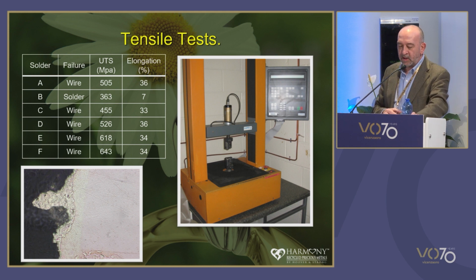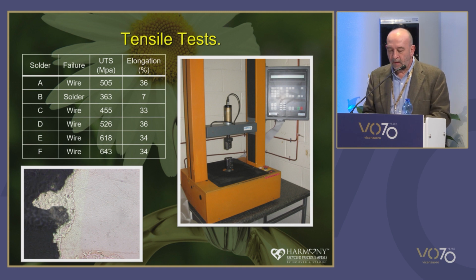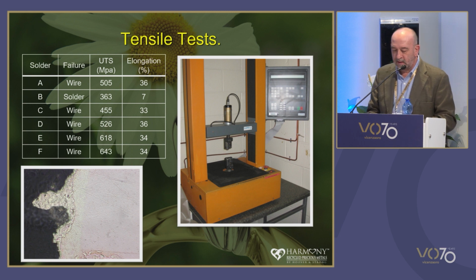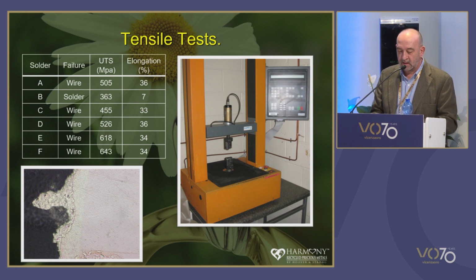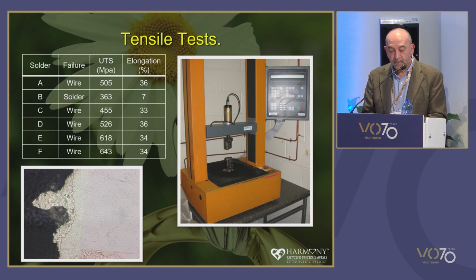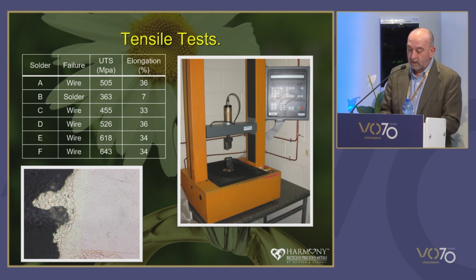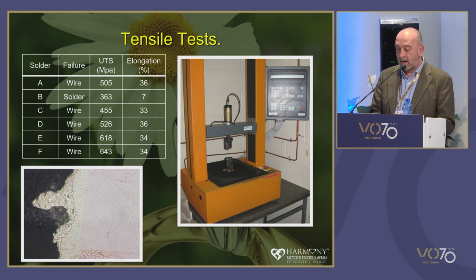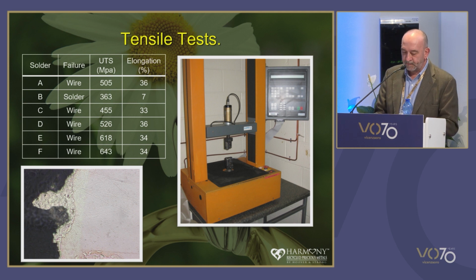So a quantitative measure of the strength of a solder and the solder joint can be determined by butt joining two pieces of ground wire together and then performing a simple tensile test. The important factor here isn't so much the numbers, but whether the sample fails at the solder joint or whether it fails in the wire. If it fails in the wire, the solder joint is at least as strong as the parent metal. If it fails in the solder joint, it doesn't necessarily mean the solder is not suitable for manufacturing, providing the breaking stress is high enough.